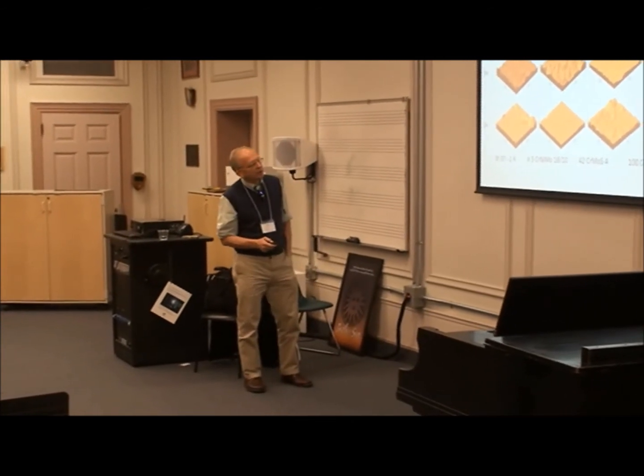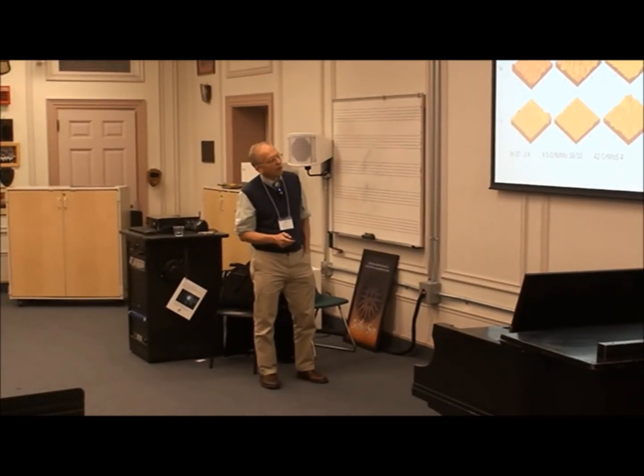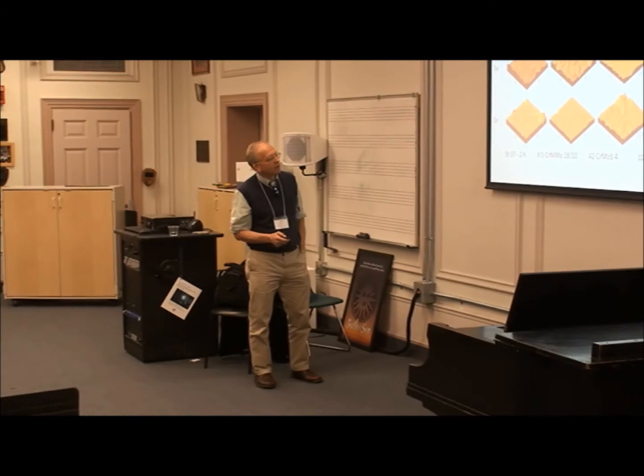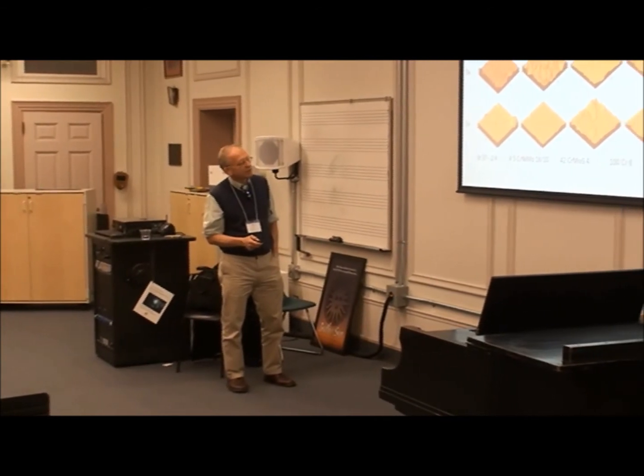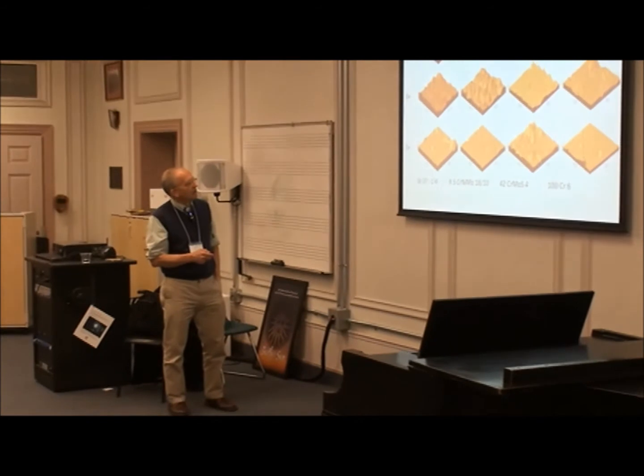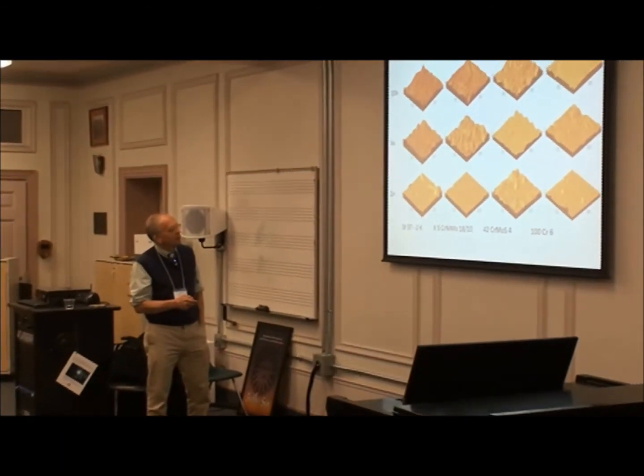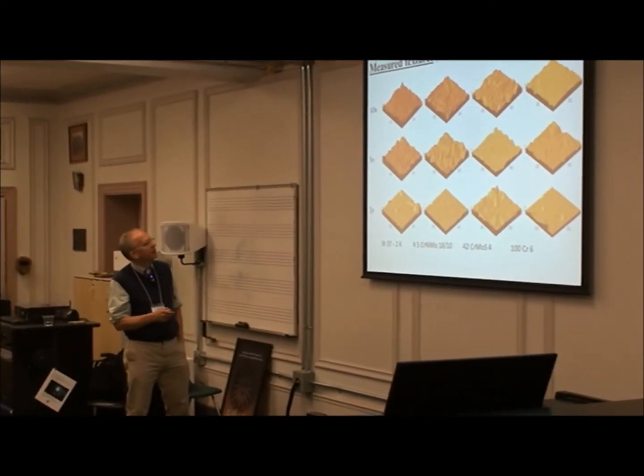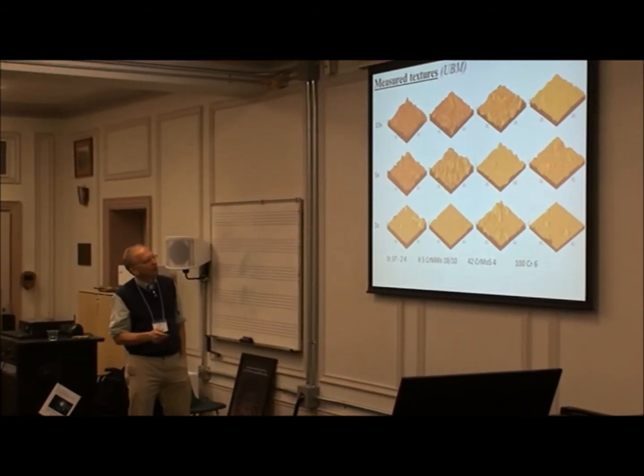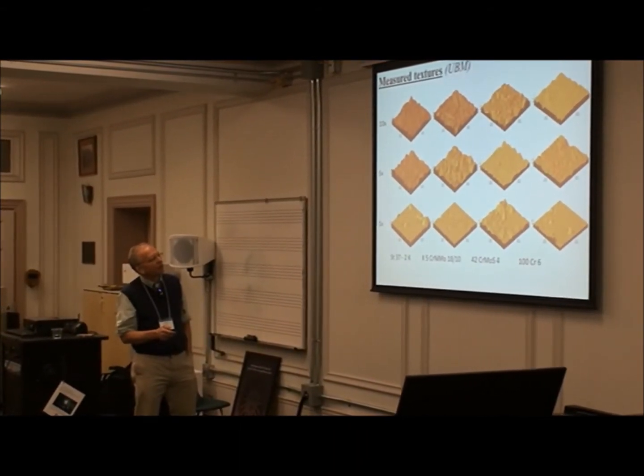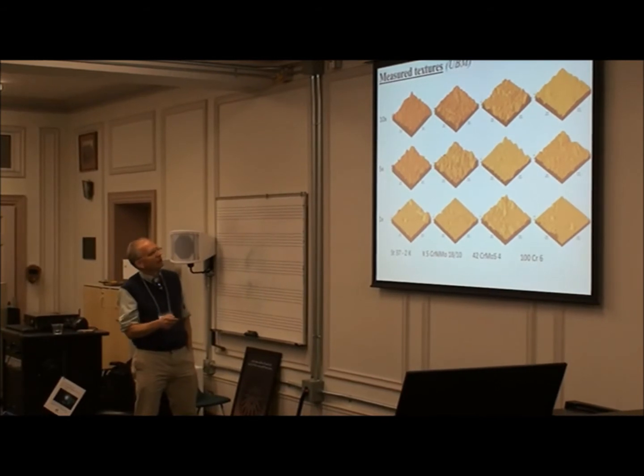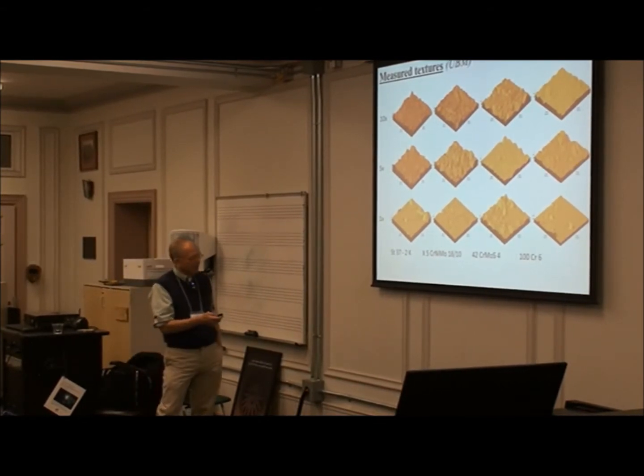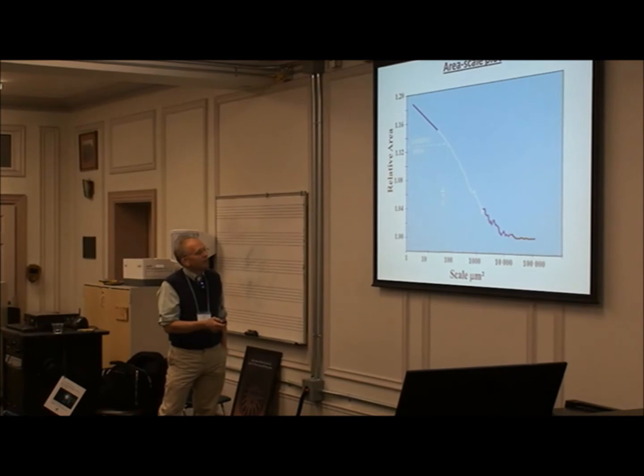And so these are some of the measurements. These are actually pretty cool. So here's the hard one. You can see impact from one grit on the surface there as it goes in, skids to a stop and piles the thing up. And here in the softer one, you see the same thing, but it's a bigger pile up in the intermediate ones. And after 5 times, you can't really distinguish individual ones very well. You still see some stuff that might be unaffected. And after 10 times, the whole surface is completely beaten up. So that sort of made sense. Now what we're shooting for is the right scale, so that it gives us the right relative area for that interaction.